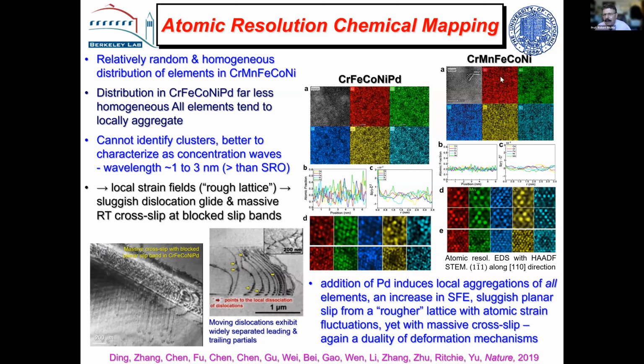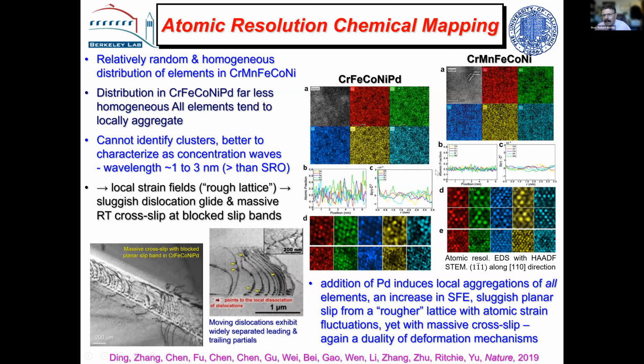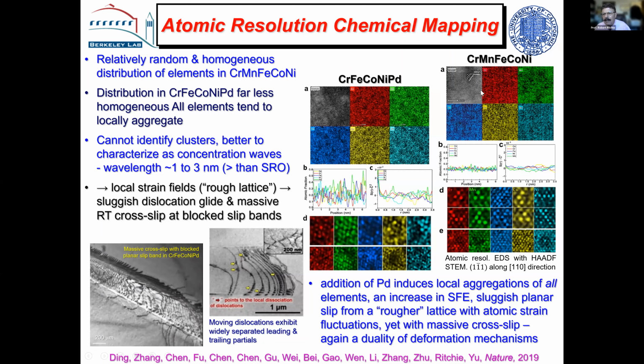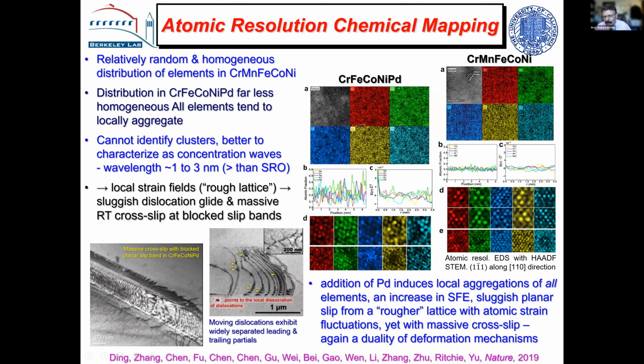And in the case of the chrome, manganese, iron, cobalt, nickel, there's basically a randomness. You've got 5 elements, so it should be 20% of each element in each column if it's random, and that's what you see. But in the palladium one, we got tremendous variations, which in some cases varied from, should be 20% if it's random, but went from sort of 5 to 45.